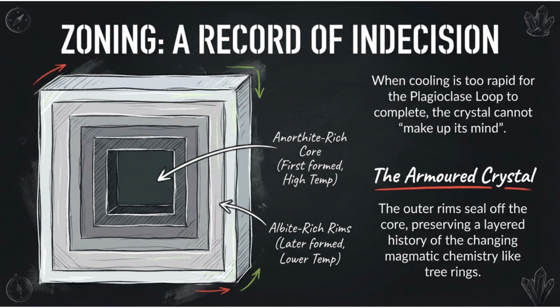Sometimes cooling is too rapid for plagioclase crystals to fully keep up with the ideal solid solution path. In these cases, the crystal cannot completely make up its mind about its composition, and zoning develops. The core of the crystal forms first at higher temperatures and is richer in calcium, reflecting an anorthite-rich composition. As cooling continues and the surrounding melt becomes more sodium-rich, successive layers added to the outside of the crystal become increasingly albite-rich. The result is a zoned crystal with an anorthite-rich core and albite-rich rims.